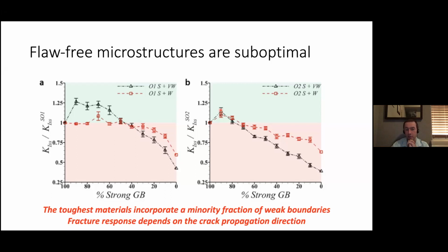On the other hand, it means that if you have made a material that is relatively flaw-free, then as it deforms and new flaws are formed, it might actually get tougher. Now, that's of course assuming that you don't exceed some critical fraction of those weak boundaries. When the boundaries all become weak, then the material becomes weak as a whole. But there is some range of weak grain boundary fraction that will actually toughen the material.